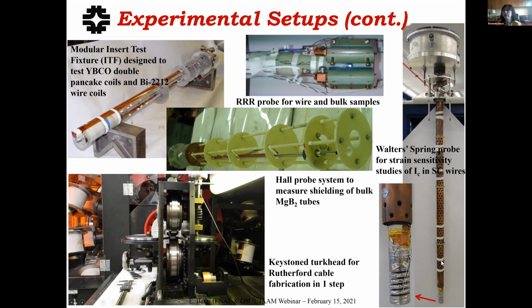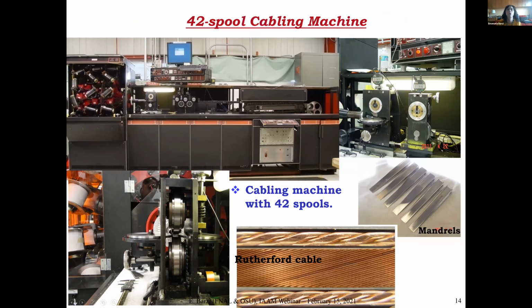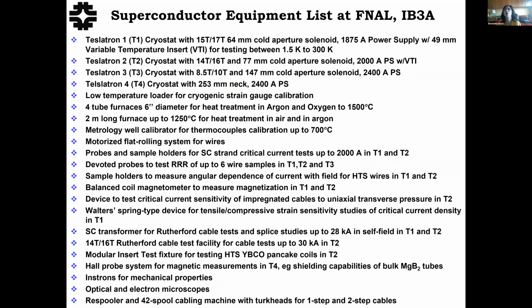This is a Walter spring device that we designed to measure the strain sensitivity, the axial strain sensitivity on wires, as I mentioned, on niobium-tin and niobium aluminum wire. So just to give you an idea, this is the cabling machine. These are the mandrels that are inserted, held into this Turk head from this side, and the wires are wound around, and then out of this Turk head you have your Rutherford cable completely formed and flat. So anyway, this is just to give you an idea. This is a list of equipment.